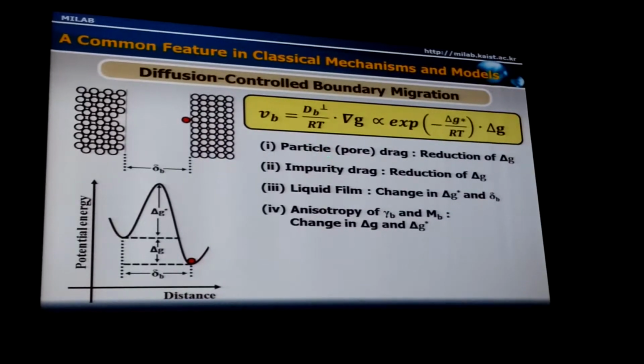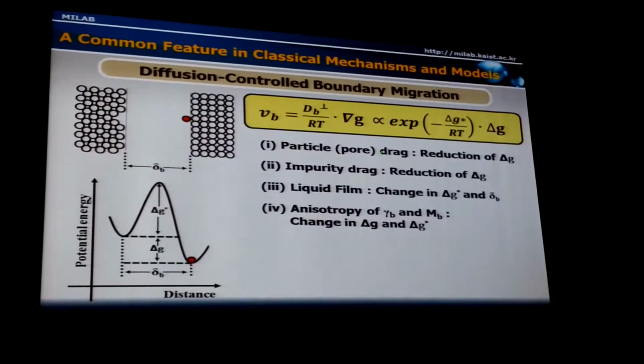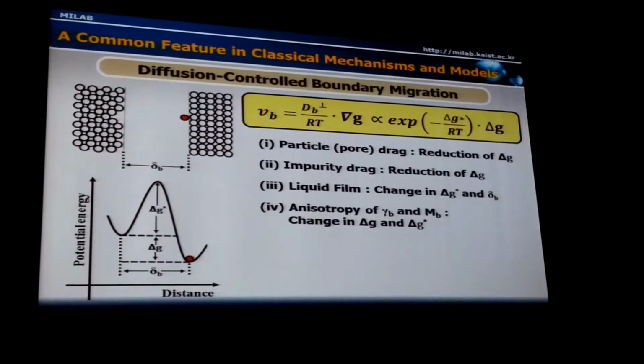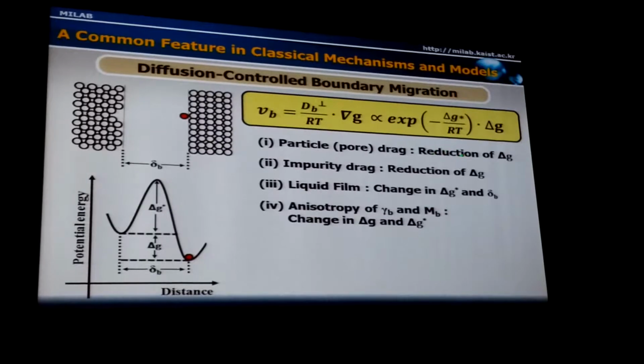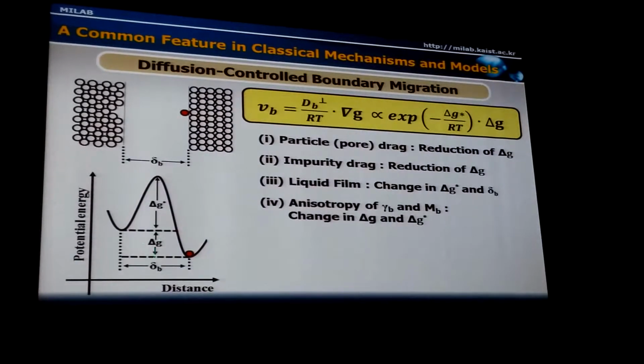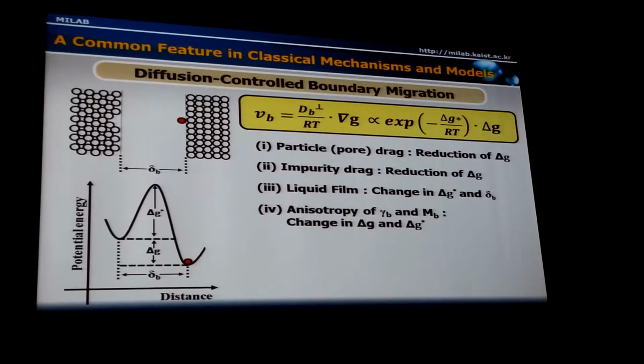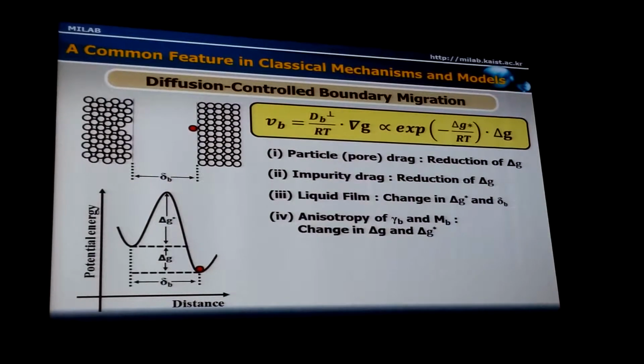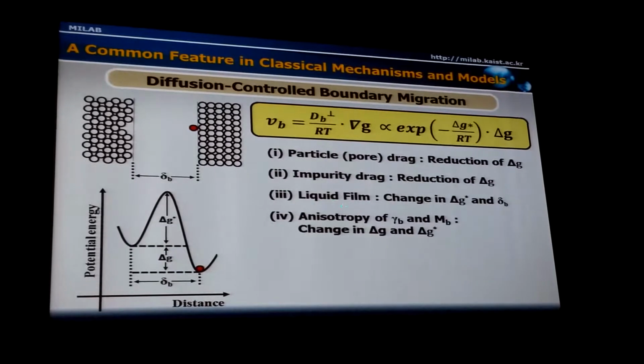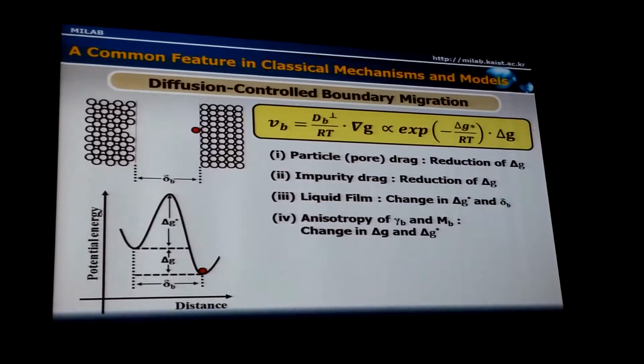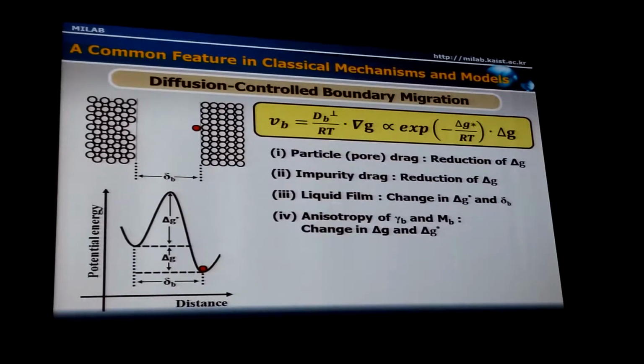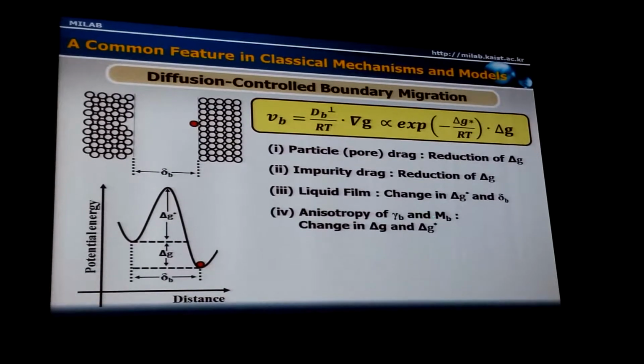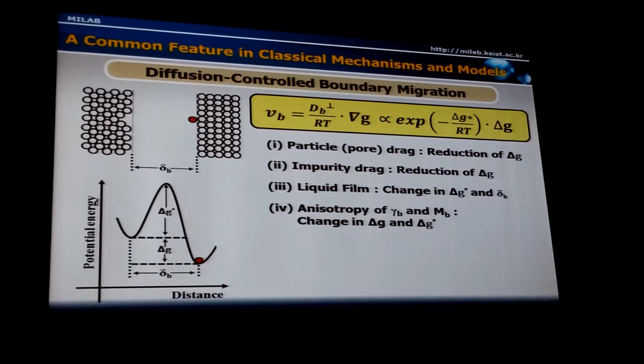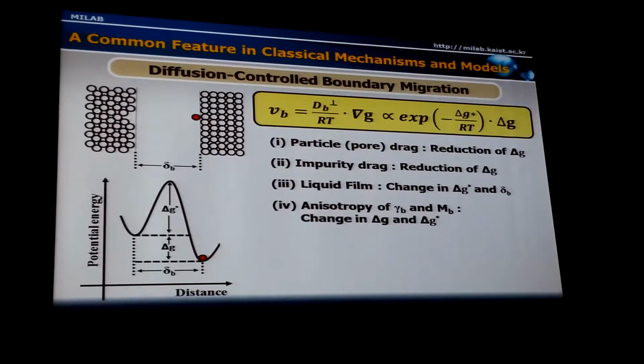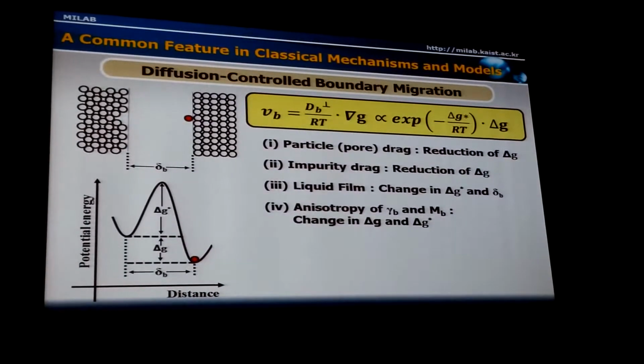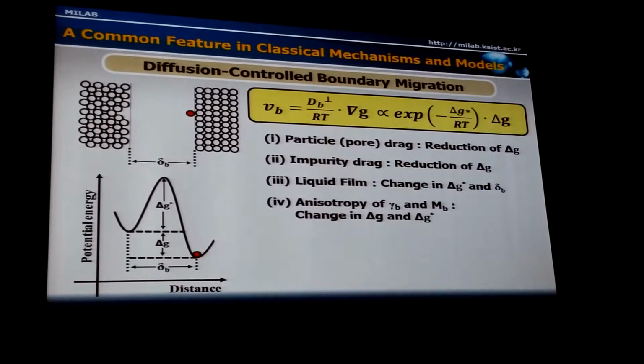For example, in the case of second phase particles dragging the boundary motion, the effect appears as a reduction of the driving force, delta G. And when impurities are present at the boundary, this effect also appears as a reduction of the driving force. When there is a liquid film, it changes the activation energy and also the diffusion distance. And when there is an anisotropy of grain boundary energy and mobility, it also affects the driving force and the activation energy. But the mechanism itself was assumed to be diffusion control.